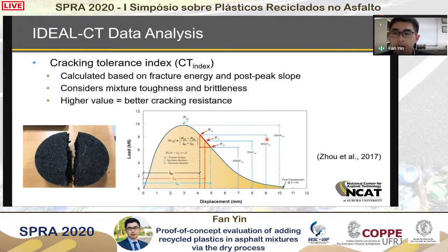For the cracking evaluation, we look at IDEAL-CT. This is probably one of the most popular cracking tests used in the United States under the framework of balanced mix design. It is very similar to the way we run the TSR. It's an indirect tensile test. We apply the load in the vertical direction, and we measure the load versus displacement.